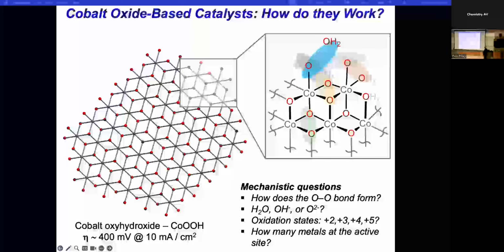Well, the cobalt oxide that seems to really do this chemistry is this layered oxyhydroxide. And the chemistry is believed to occur at an edge site, at a site something like this, shown here in this blow up. So in terms of how the OO bond forms, there seem to be a lot of possibilities. And I drew out here, I think, six different OO bond forming events you can imagine based on different oxygen species at that edge structure. So we wanted to get at that and probe that.